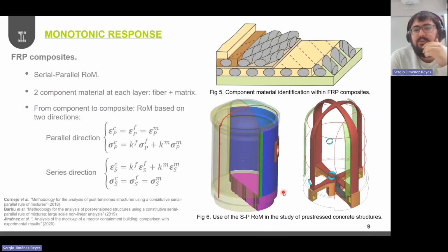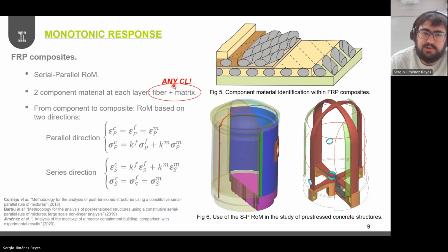And then when moving towards the characterization of composite materials, and in particular towards FRP composites that are the ones being studied in the Fatigue4Light project, we use this serial parallel rule of mixtures approach. And this is indeed an evolution of the classical rule of mixtures, where for each of the layers of the FRP material, we distinguish two component materials, the fiber and the matrix. And for each of them, we can use any constitutive law. So at the end, what we are doing here is characterizing the component materials composing the composite, and then building up the composite response through this serial parallel rule of mixtures.